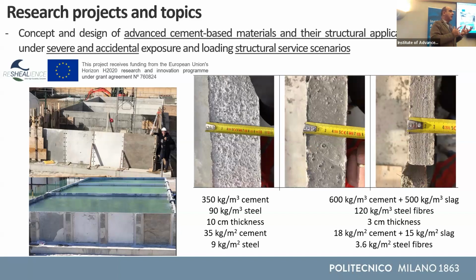So we changed the structural concept going to a slab because the slab is a redundant structure. It can redistribute stresses, it can exploit the properties of this material. So even if the mixed design, if you look at the cubic meter of this material, you have more cement than in ordinary concrete. But if you compare the square meter of a wall, you see that in this case, 1 square meter contains 35 kilos of cement. In this case, it contains only 18. And even if you add slag, which is a supplementary cementitious material, the sum is still lower than that. So this is the way to look at the use of ultra high performance construction material, whatever they are.